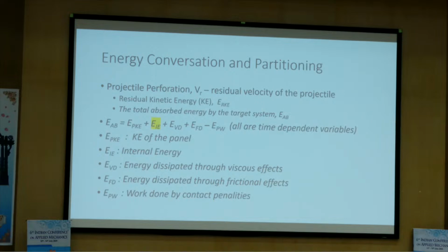One thing these people did, the energy partitioning. They tracked all the energy due to friction in the interface between the 2 plies, right? Delamination, energy goes to delamination, energy goes to rupturing the fiber, energy goes to fiber bundle sliding failure. So all this damage model consumes energy. So the projectile's kinetic energy, the total energy, is going to be dissipated, dispersed through wave propagation and damage, deformation, and you keep track of them. Now, you get a wrong result if you don't keep track of the energy correctly. If you lose energy, that means you are doing something wrong. When you do Abaqus calculation or any code calculation, keep an eye on the energy term. You might have put some wrong parameters inadvertently, and then what you do is make sure that your calculation is correct and you are getting realistic and meaningful results.